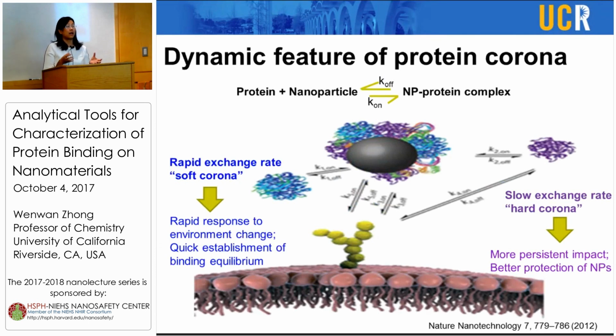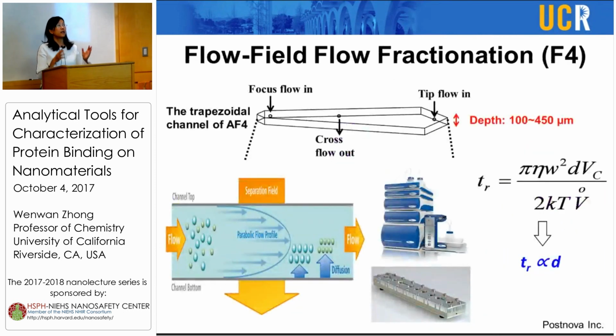However, the hard corona is the one that could carry some of the proteins within it, because they have a very slow dissociation rate towards different environments. For example, they could be formed in the extracellular matrix and then be carried into a cell. So the relative components in the soft and hard corona is what we are interested in, finding how the surface property of the particle will affect their formation.